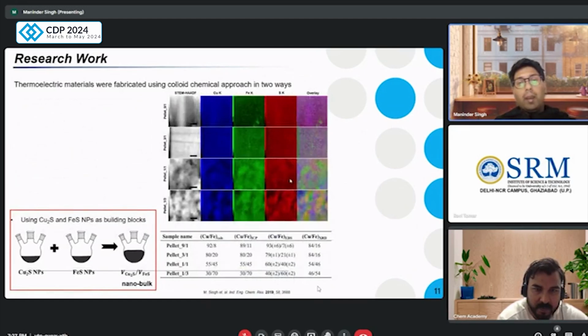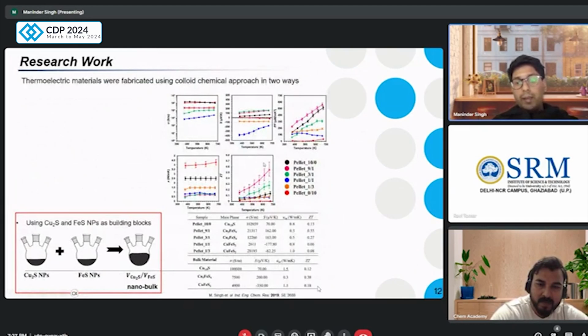In the research work that I was doing, I was trying to increase the thermoelectric efficiency of the material, and I succeeded. Basically, this chart is the ZT value. This chart helps us understand whether we succeeded in increasing the thermoelectric efficiency. This pink line tells us that with this nanoparticle solution, copper iron sulfide nanoparticles, we achieved a good thermoelectric efficiency overall. And if we compare with the literature work, it's much more. So what we do is create nanoparticles and compare them with the bulk material. The thermoelectric efficiency that we got is 0.55, and that is much more than the existing literature value. So we succeeded in our research work.